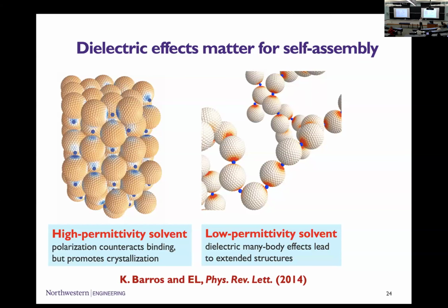So imagine now you have a particle on the North Pole and one on the South Pole. But because the whole surface of this white ping pong ball has to remain neutral, the entire equator now is negatively charged. And you start to repel additional particles. And that's why you get these elongated structures, why it gets so open. Because the equatorial region is no longer attractive to anything else.